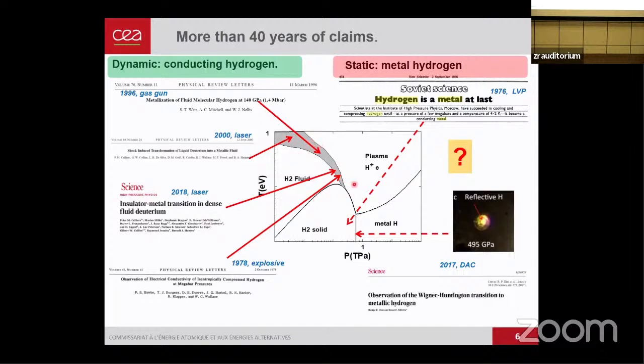The issue is that the pressure temperature locus is not very precisely known, but roughly the various measurements have been going up to 10,000 K down to a few thousand K. And you see, as you increase pressure, it's at lower temperature. So it's becoming a density effect, a transition induced by density, like metallization.